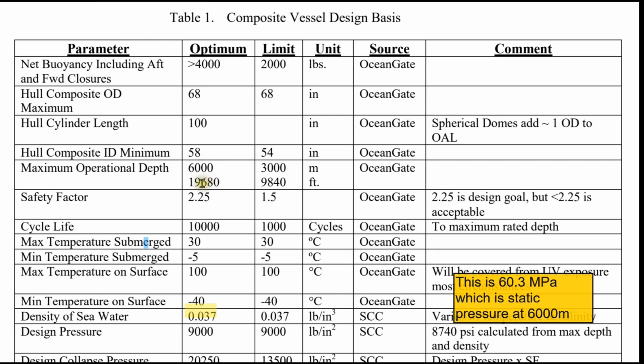that the Titanic is actually only at 4,000 metres, and this with a factor of safety of 2.25. And we're aiming for 10,000 dive cycles with a minimum acceptable value of 1,000 dive cycles. And this equates to a design external pressure of 9,000 psi or 60 megapascals with a collapse pressure of 20,000 psi, which is 9,000 psi multiplied by a factor of safety of 2.25. And clearly, if we can achieve all of this, we've got a hull which will meet all relevant design requirements.